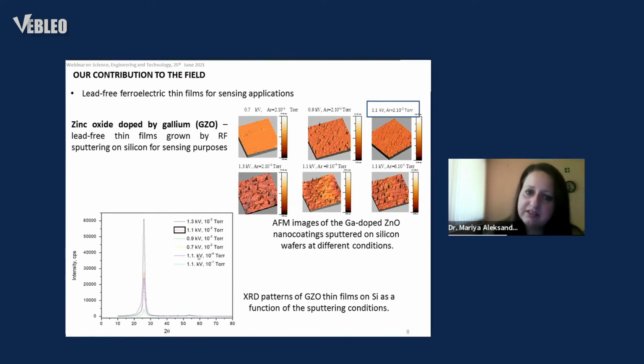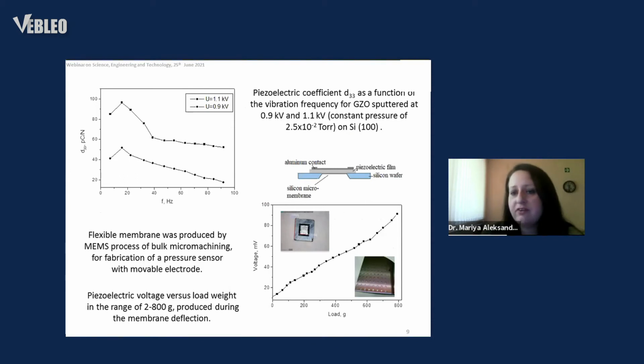Then the second criterion is to form a crystallite structure, not amorphous, because otherwise there will be no polarization effect in these coatings. So from the two combinations, we select this one that is produced at the higher sputtering voltage, because as you can see from the X-ray diffraction, these peaks and their sharpness mean that a specific crystallite formation following single axis orientation is growing, and this is favorable for the polarization process. So this case we select for further fabrication of our device.